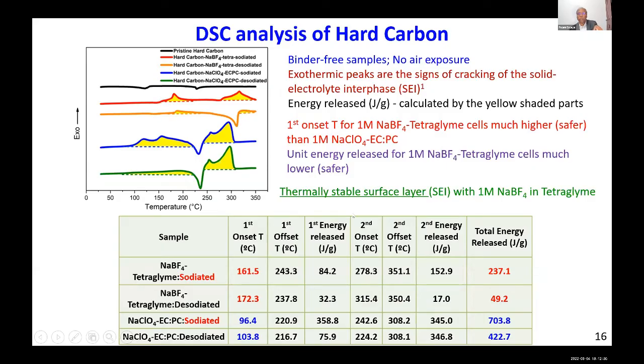And the energy involved, that is the area under this curve, is about 237 joule per gram in tetraglyme. Whereas if I take carbonate-based electrolyte, you can see the thermal event happens even at a much lower temperature, and the amount of energy released in the sodiated hard carbon using carbonate-based electrolyte is much larger than the glyme-based electrolyte. This tells you that the glyme-based electrolyte is safer when it is used along with the hard carbon or sodium titanate or any other anode material.